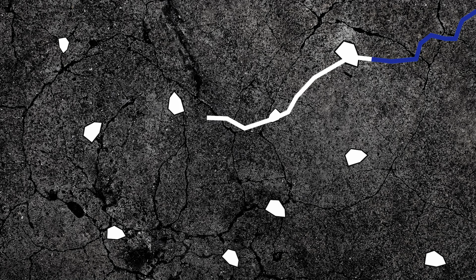As rainwater later permeated those cracks, this material could react with water, creating a calcium-saturated solution, which can recrystallize into calcium carbonate and quickly fill those cracks, or react with volcanic ash components, further strengthening and healing the material. Well, can they prove it?